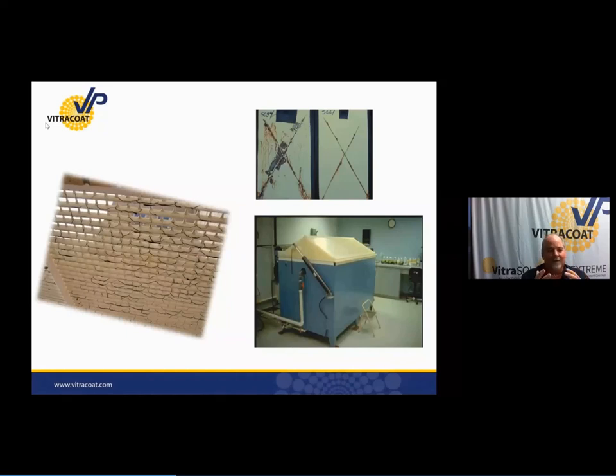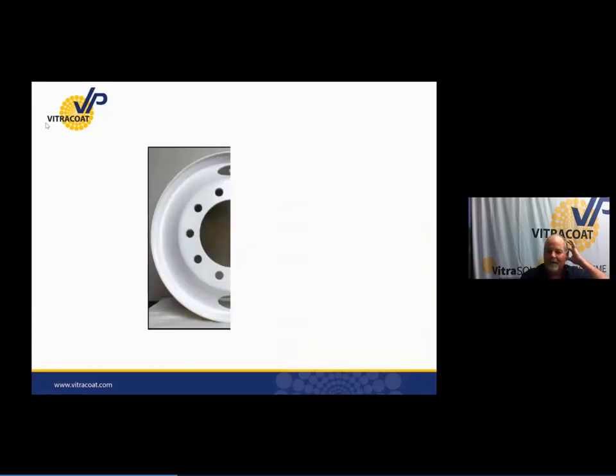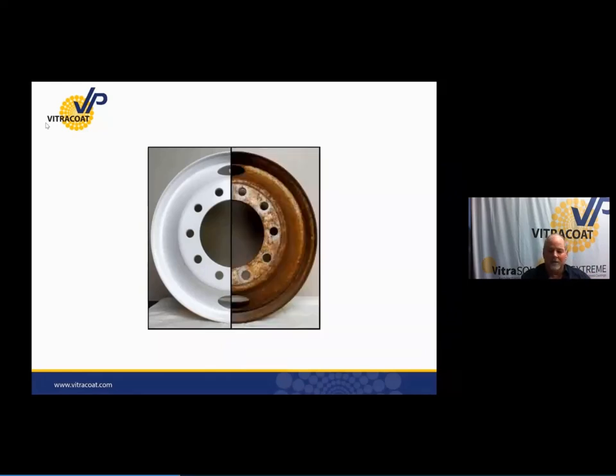It's because obviously the panels aren't going to dictate or be 100% representative of your part. Now, that's an obvious answer. I mean, I give you that one. There's also some more detail I want to go through. The reason that the part I showed earlier corroded really, really bad and the coating actually peeled off of it is because this is what it looked like when it came out of the oven, but this is what it looked like before it went into the coating booth. So you have to have a good representative of what the panel may look like.